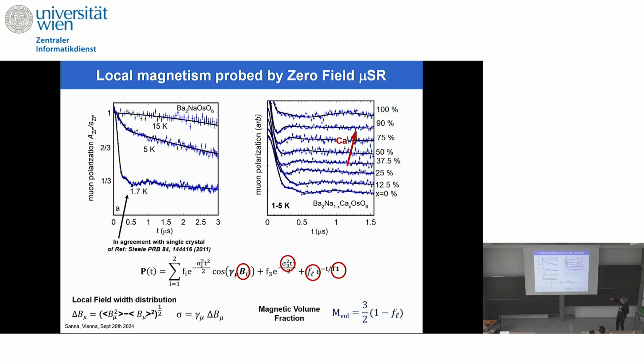How does it change when you dope the system, going from sodium to calcium? You have something which is maybe similar to an oscillation, possibly. The recipe to fit the data is the same, but you see that there are not very convincing oscillations. At least one part of the signal is always a very fast decay, which means a sort of disorder, a distribution of local magnetic fields.